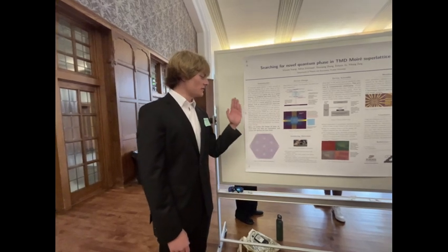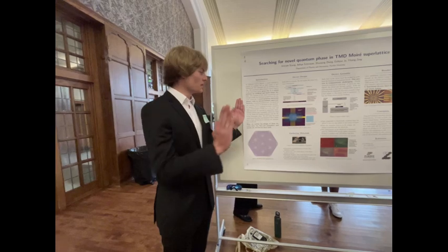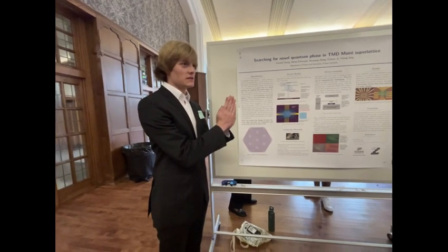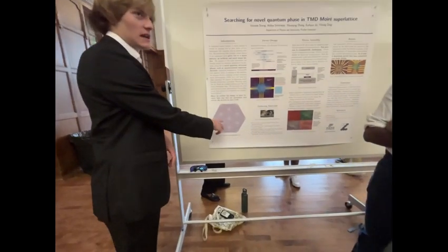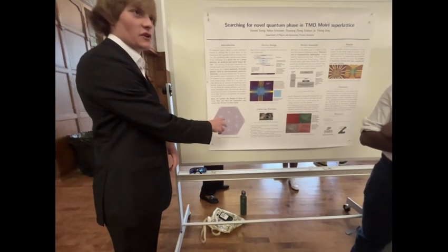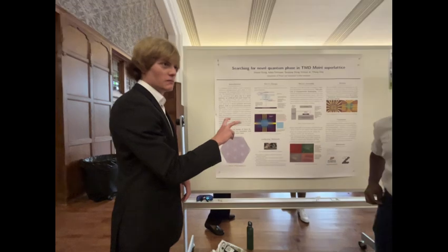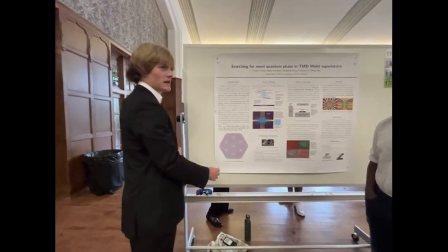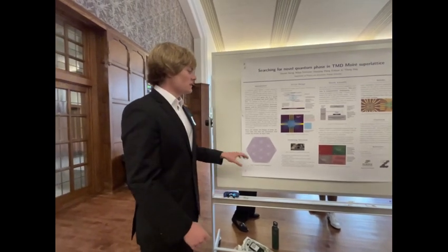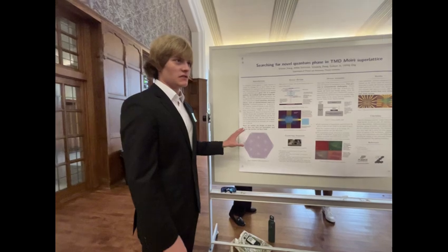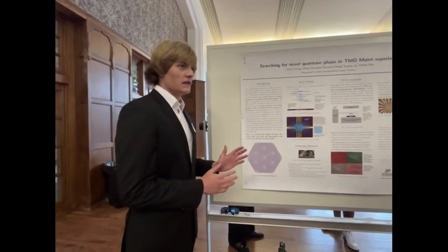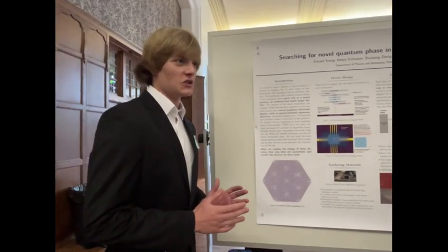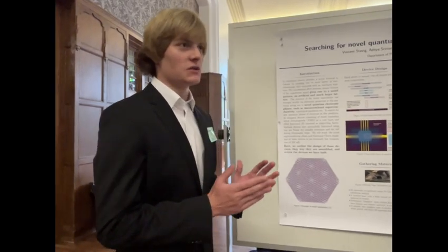Right. So if you imagine this is one sheet of graphene, this is another. When you bring them onto each other and twist them at some slight angle, the two lattices, and that's what's happening in this figure, they basically interfere with each other to give rise to a larger Moiré superlattice. So that's what's happening with this hexagonal structure that comes out of that. And what's interesting is that when you do this and you make Moiré superlattices with 2D materials, the angle in some cases will actually change the way the electrons behave in those constituent layers used to assemble it.